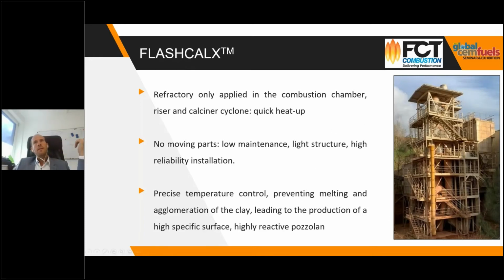But the main characteristic of this type of equipment is that you have a very low amount of refractory. So refractory you have basically only in this calcining part, and this gives a very fast heat up of the system. So you can start heating the system and producing a couple of hours later on. You have virtually no moving parts. This means, except for fans, you have no moving parts, so a very robust and low maintenance light structure, very reliable. And as you know from the clinker kiln, you have a very precise temperature control.